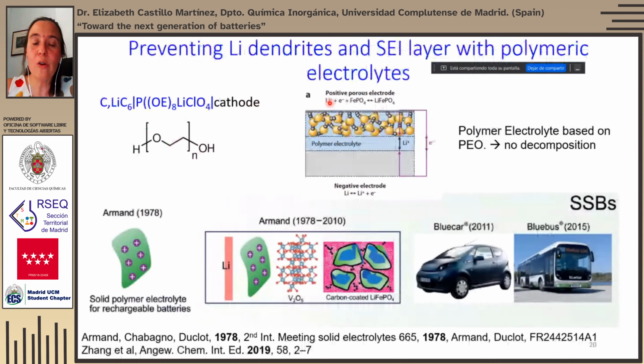So what can we do? Instead of a flammable electrolyte, we can use solid electrolytes. And here there have been different strategies. One of them has been the use of a polymeric electrolyte, which was proposed by Professor Michel Armand already in 1978, where he proposed a rocking chair battery made of a cathode and a graphite anode. To make the contact between the cathode and the polymer electrolyte with less interfacial resistance and to help the lithium-ion charge transfer, typically the polymer electrolyte and the cathode are mixed on the cathode side. There is, of course, then a layer of polymer electrolyte free from the cathode.